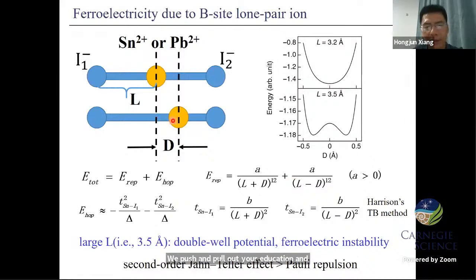Another effect is the bonding effect. For example, the empty p orbital of this can interact with the occupied p orbital of the atom. The energy of this kind of interaction can be written in this form according to perturbation theory. This is a hopping between these two, and we can write it in this form. It depends on the distance between the cation and the anion, and we use this formula according to Harrison's tight binding method.